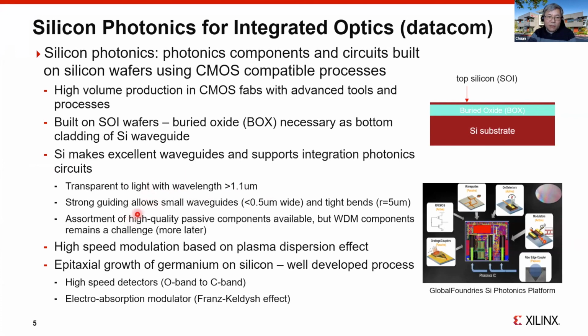So silicon actually makes an excellent waveguide because of the high index contrast between silicon and silicon dioxide, which is the cladding for the waveguide. The silicon waveguide is called a strong guiding waveguide, so it can be made very small in width. A typical single mode silicon waveguide is less than 0.5 micron in width. And because of the strong guiding, you can make pretty sharp bends of the waveguide without much bending loss. The typical bend radius for a silicon waveguide can be below 5 microns.